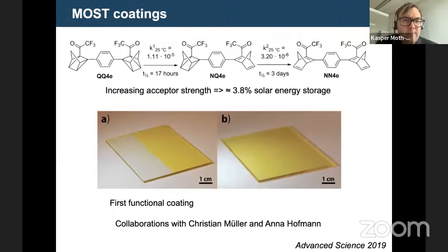So in our first attempt here, we made a little bit improved system. You can see you have two norbornadienes with the bridge and a little bit stronger acceptor. And with this, we can store the energy for some hours. We can put it in a coating. It's yellow, but when it's exposed to sunlight, it becomes fully transparent. And this molecule can capture up to 3.8% of the incoming solar energy.